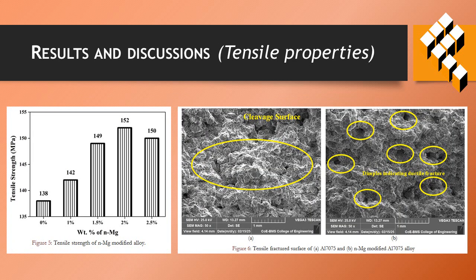Figure 5 shows the tensile strength of the nanomagnesium modified alloy. From the outcome, it is observed that up to 2% of nanomagnesium, the tensile strength was increased due to the high brittle hard particulates. Whereas in the 2.5% nanomagnesium modified alloy, the tensile strength was reduced due to the agglomeration of high weight percentage of nanomagnesium particulates. Figure 6 shows the fractured surface of the tensile samples.